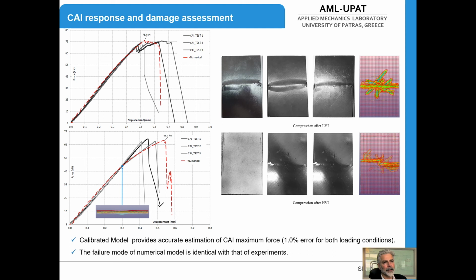There is a difference in maximum force at the level of 1%. It also captures the behavior of the material very well. If you see in the pictures, you see also that the way samples fail is captured very well in both cases, low and high velocity impact. So this simulation is also very successful using this calibrated material data.